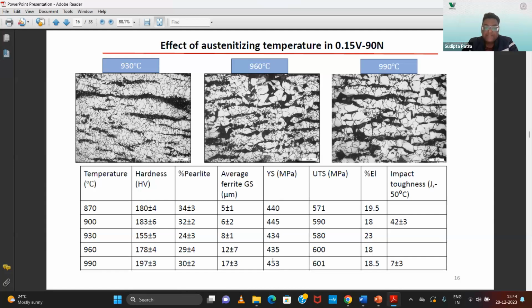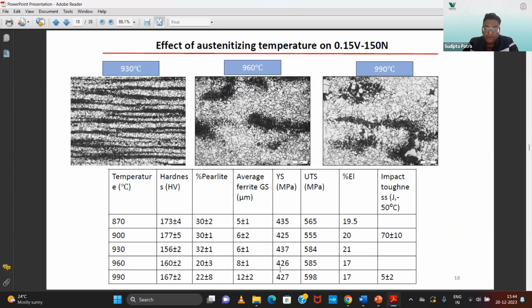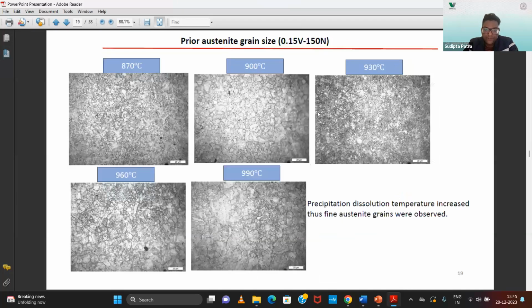First it is decreasing and then it is increasing due to the high precipitation strengthening when the precipitates are dissolved state and then reprecipitated. So again we have taken this 150 nitrogen steel at higher temperature. We can see that the vanadium precipitates did not dissolve here, as the precipitation stability is high in case of 150 nitrogen. So in this case we have observed that the high nitrogen content can lead to very good grain refining, and the grain will not grow because of the precipitation stability in case of high nitrogen and high vanadium steel.